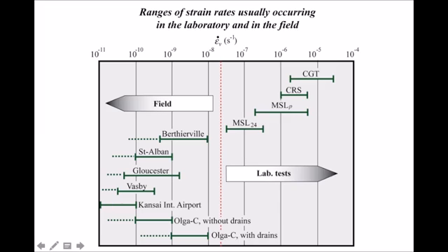So the strain rates, typically the strain rates in situ are smaller than the strain rates in the lab. Consequently, in our strain rate model, the compression curve followed in situ should be below the compression curve followed in the lab. Smaller strain rate, effective stress. So it's what we have examined.